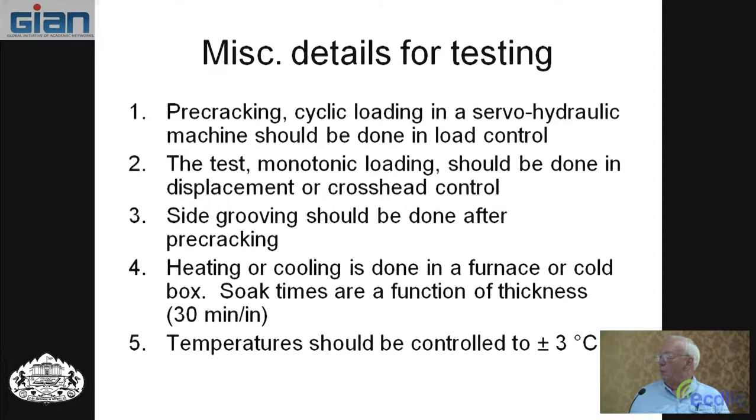Normally, you test at other temperatures than room temperature. And if you're either heating or cooling, you should do a soak time, 30 minutes per inch of thickness. And that could be 30 minutes per 25 millimeters. So normal test specimens, if you're using engineering units, normally you have an inch thick. You can have thicker, but often it's an inch thick. If you're doing SI units, normal is 25 millimeters. So you should soak 30 minutes.